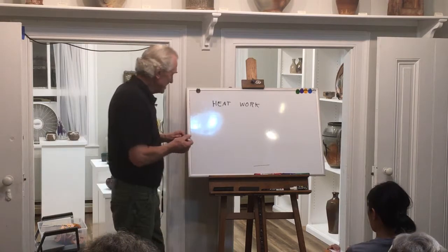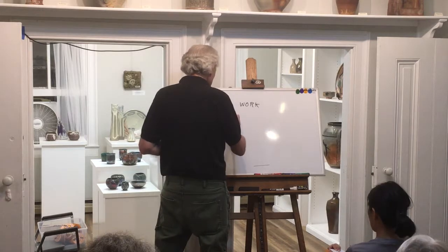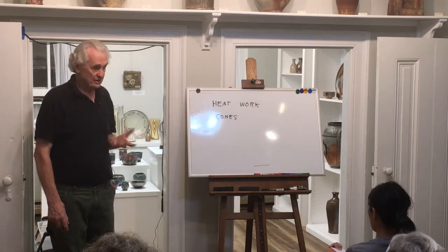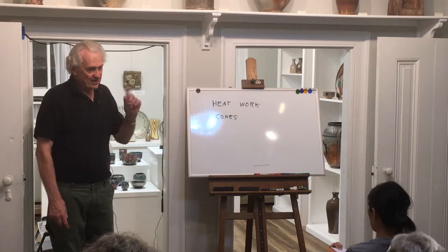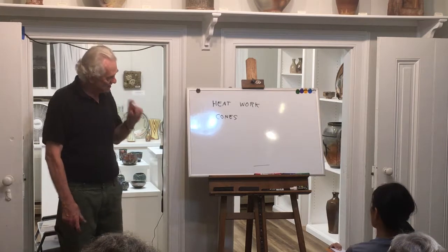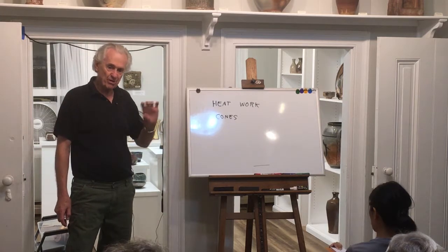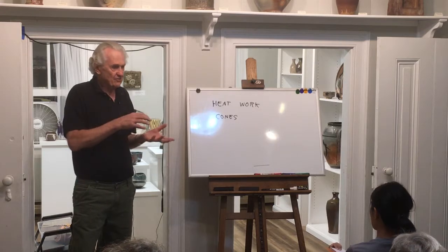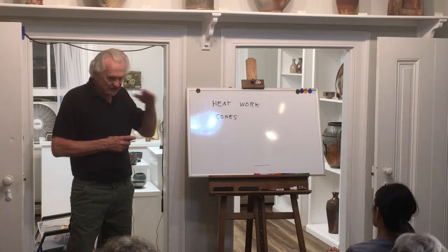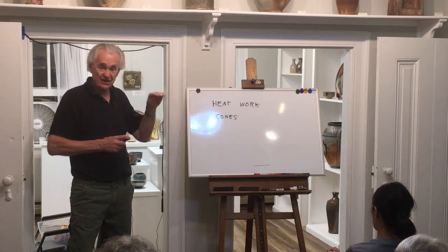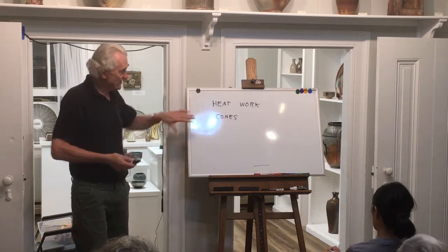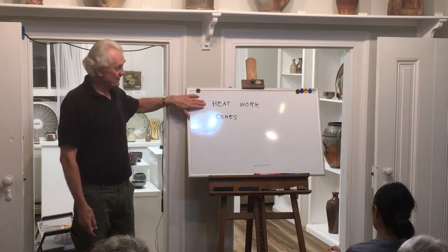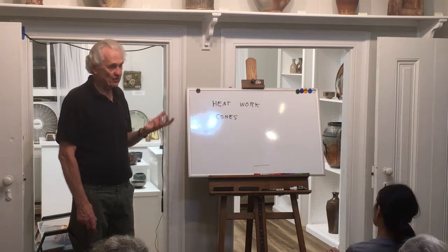So we really talk about heat work, and this is why we talk about cones, because cones respond to heat work. Because cones, in fact, are little clay bodies. And so the way a cone responds to heat and time is exactly the same way our pots respond. They soak it up, those changes are going on inside, and they respond to it. So temperature is just an instantaneous tell of something going on, but it doesn't tell us how the pot is actually responding. So that's what cones are doing. Cones are measuring or reflecting heat work. And that's the way we should fire, because you need time for all those things to happen.